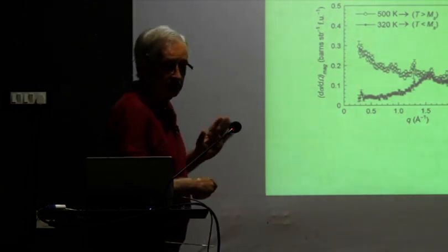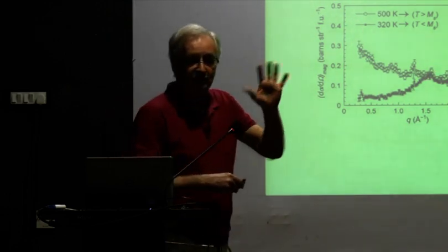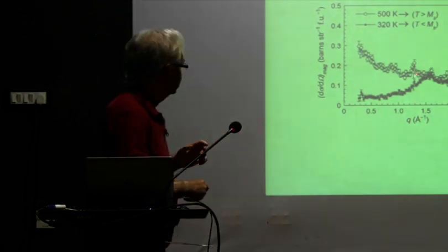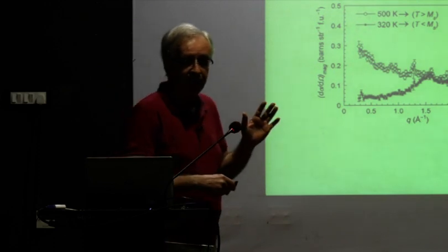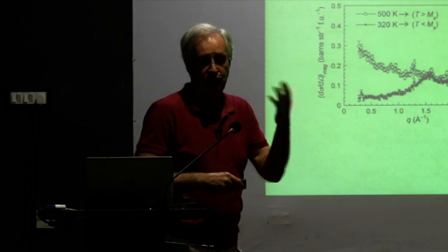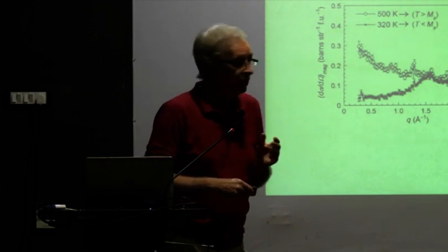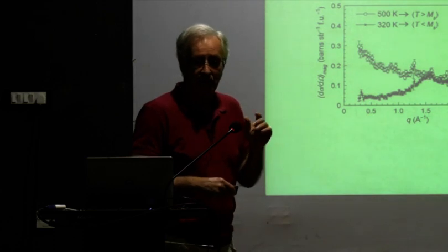In many cases, not here, you would find that this peaking would begin to look like a Lorentzian, so that it would go like this, and then it would start going up here, and then you had to stop there. And the half-width of that is proportional to your correlation length. From here, it is not easy to say what our correlation length is.